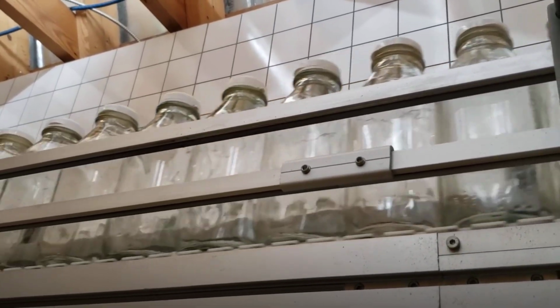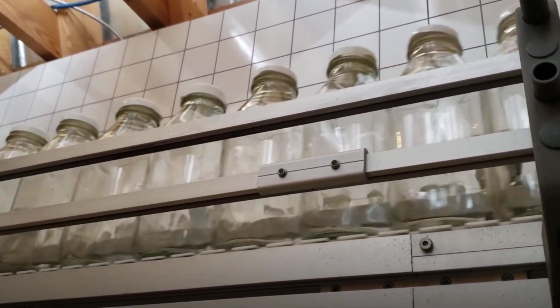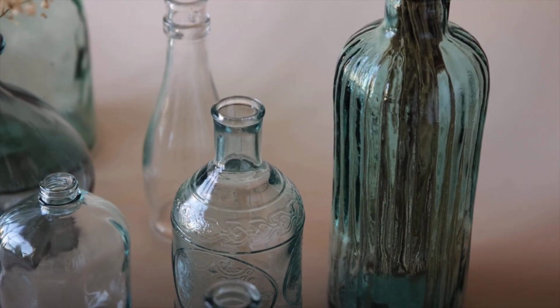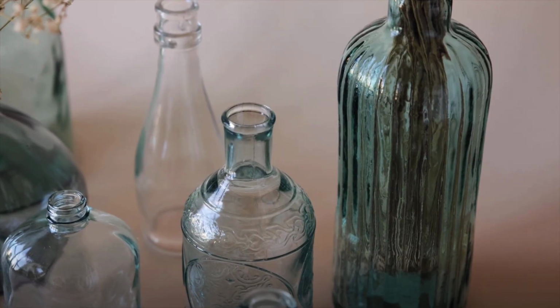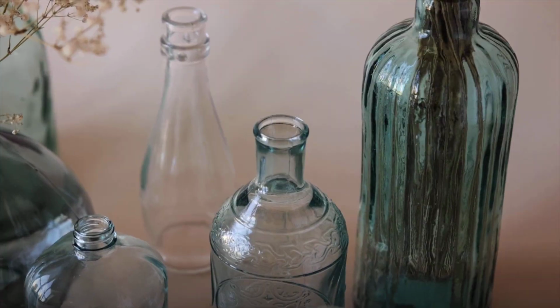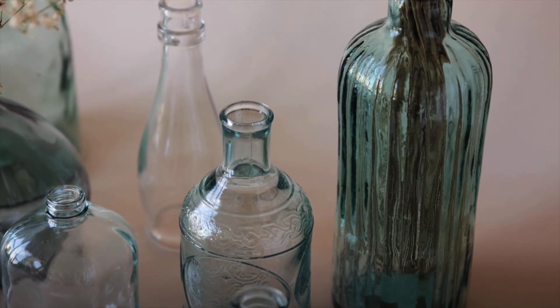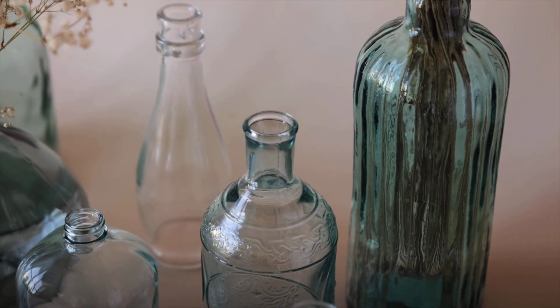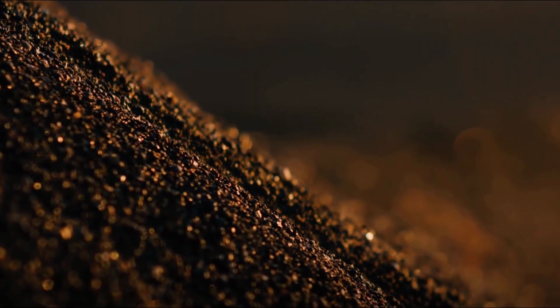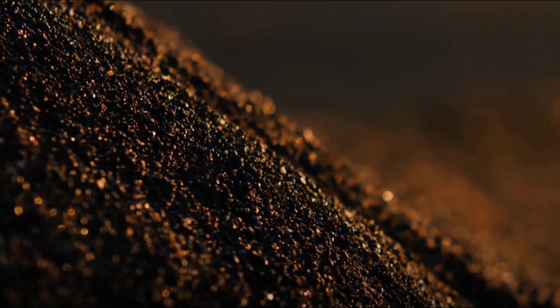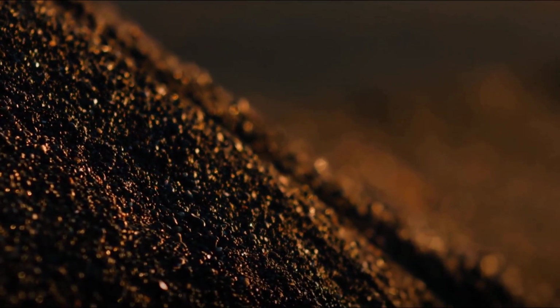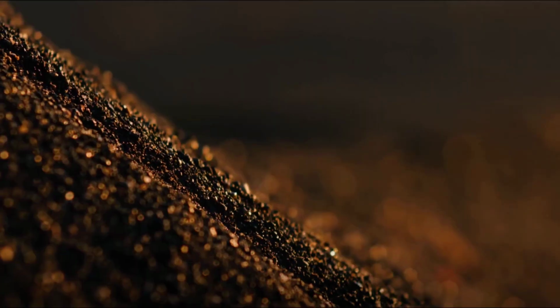First, it's one of the only materials on Earth that is infinitely recyclable. A glass bottle can be melted down and remade into a new bottle over and over, endlessly, with no loss in quality. Which is why factories add crushed recycled glass, called cullet, right back into the furnace. Second, nature makes glass too. When lightning strikes sand, the heat can fuse it into hollow glass tubes called fulgurites. And when volcanoes erupt, fast-cooling lava can form obsidian, a natural glass so sharp it was used for ancient blades and is still occasionally used in modern surgical scalpels.